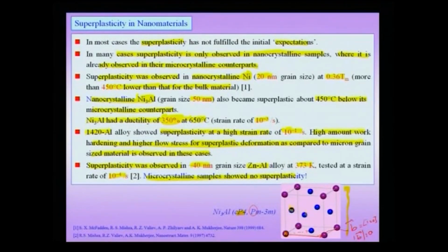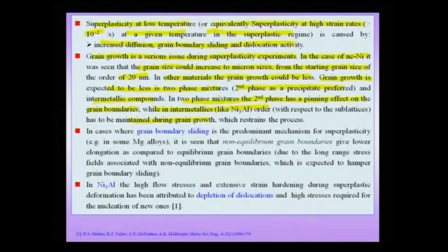my grain growth, which will have a pinning effect on the grain boundary migration and therefore lead to grain growth, or I need to work with the intermetallic, wherein grain boundary migration is also impeded by the fact that now you have two sublattices or more. For instance, in the case of Ni3Al, one sublattice is occupied by aluminum and the remaining three sublattices are occupied by nickel, and therefore this sublattice structure has to be maintained, and this means that grain boundary motion is going to be more difficult.